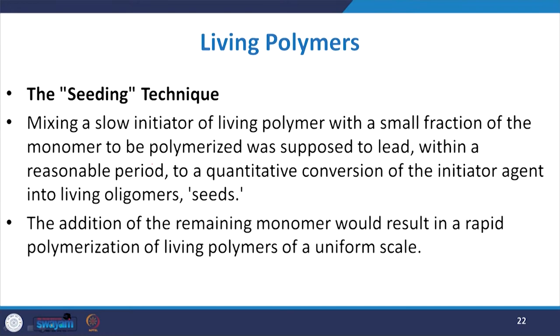When we discuss the living polymer concept, there is a technique called seeding. The seeding technique involves mixing a slow initiator of living polymer with a small fraction of monomer to be polymerized, which is supposed to lead within a reasonable period to a quantitative conversion of the initiator into the living oligomer, called the seed. The addition of the remaining monomer then results in rapid polymerization of living polymers of uniform size.